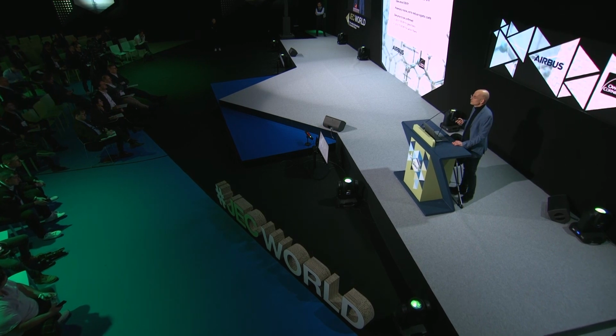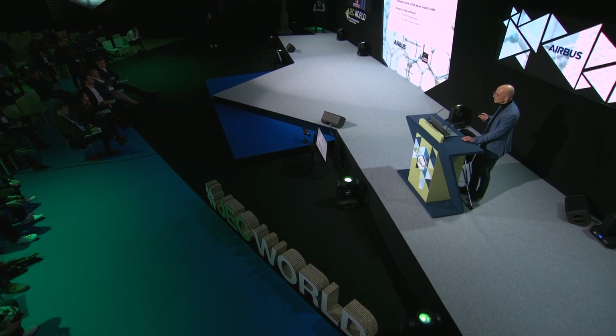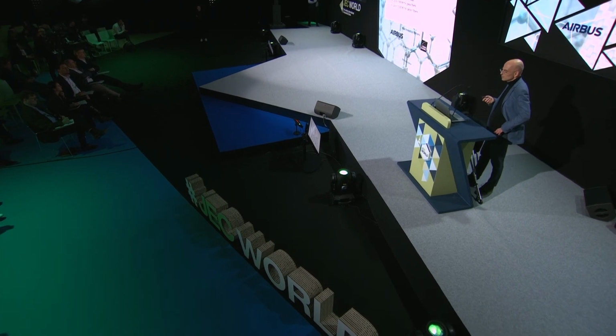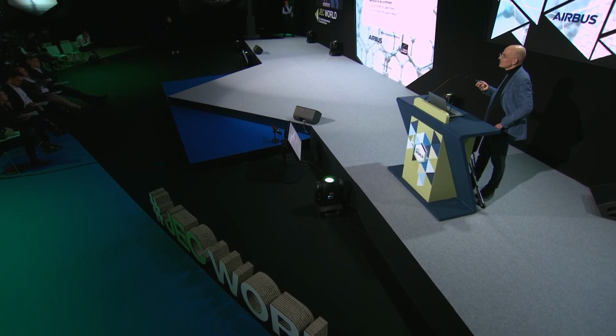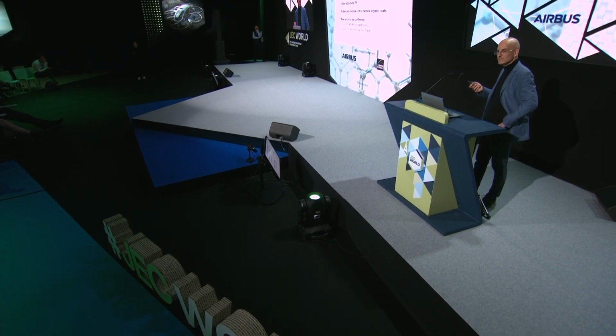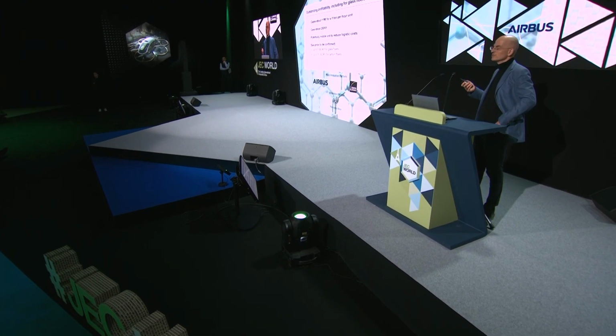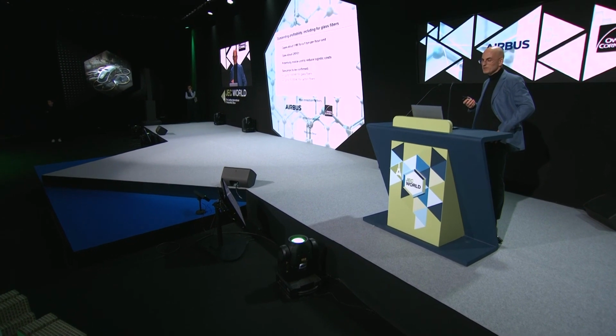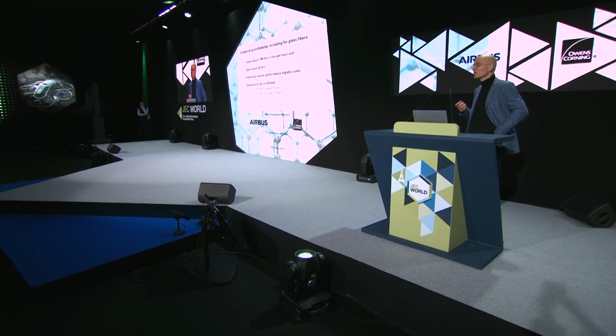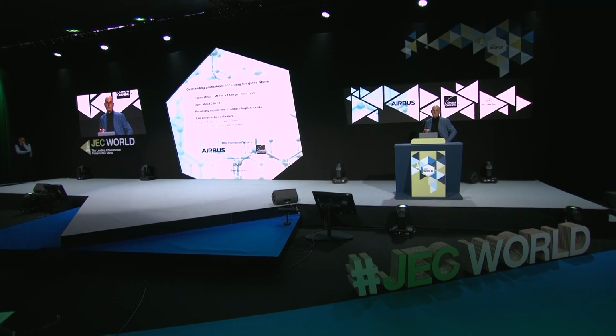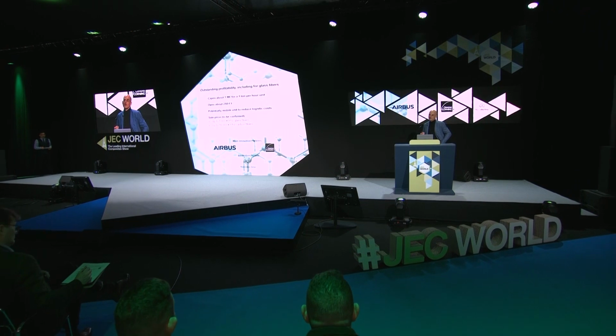To produce new products is one thing, but to do it economically is another one. So this is not really a P&L that you can see on the slide, but the CapEx is very low for 1 ton per hour, so 3,000, 4,000 tons per year. The CapEx is €1 million. The OPEX is only about 250, and we are still discussing this, and actually we are at the beginning of this journey. We think that we'll be able to sell these recycled fibers with a price of maybe €1 per kilo for glass fibers and up to €10 per kilo for carbon fibers, which is 5 times less than virgin fibers.